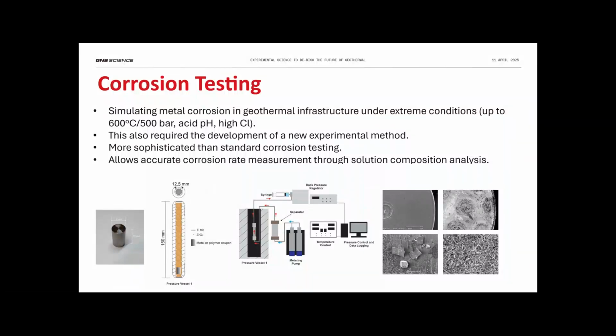If you're doing weight measurements, you can only get down to the sort of 5th decimal place of weight change. And then you have the problem of oxides forming, which increase the weight, sulfides forming, which increase the weight. So what weight changes tell you is a very rough estimate of corrosion rate. Here we can actually tell you how much iron has been lost to the micromole from the sample. So it gives a much more accurate measure of the corrosion rate of the sample.